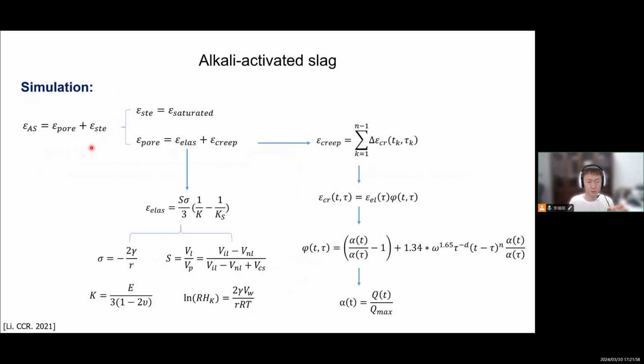So I divided it into two parts. And for the capillary part, there is an elastic shrinkage and also time-dependent shrinkage, which we call the creep. For the elastic part, one is simple. We just use Hooke's law and calculate this or measure the different parameters. It's simple, but for the creep part, we need to use some equations, which have reaction degree, water to cement ratio or liquid to cement ratio, which are K parameters, but there are some empirical numbers,